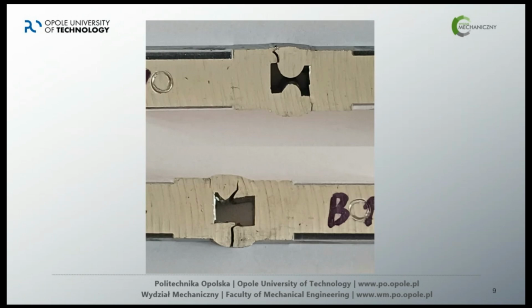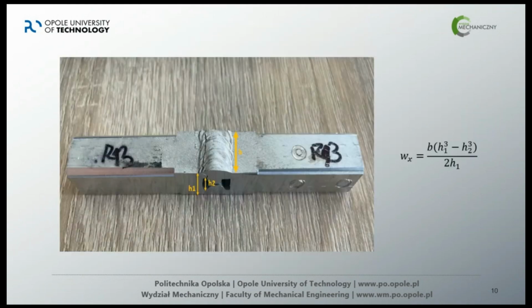On the upper photos we see typical welding cracks. The beginning of the welding fracture is in the root, but sometimes, not often, in maybe 10% of our specimens, the fracture was in the middle. Why? I don't know. It is true after experiment. Next, we calculated for every specimen this area to calculate the stress. B was always the same, 12 millimeters, and the first height was the same. The second dimension in every welded specimen had to be measured, because after welding we obtain many different dimensions.